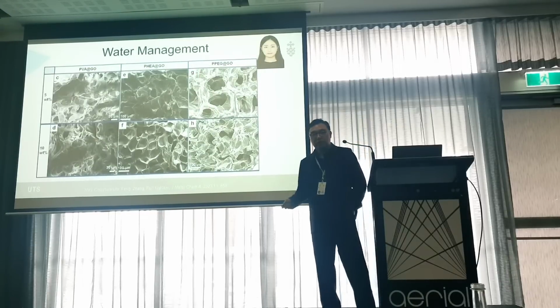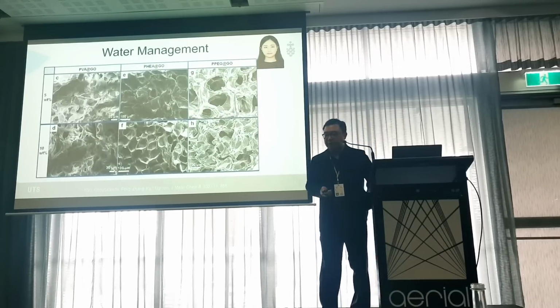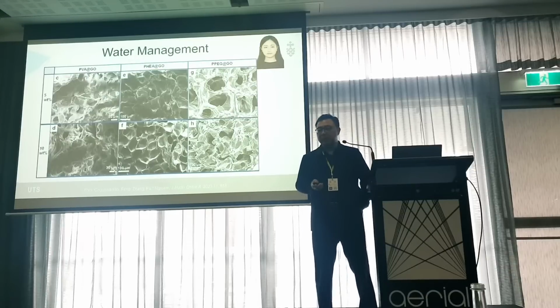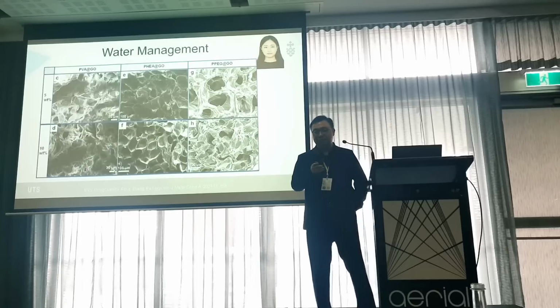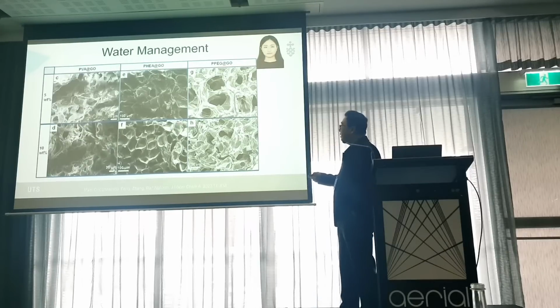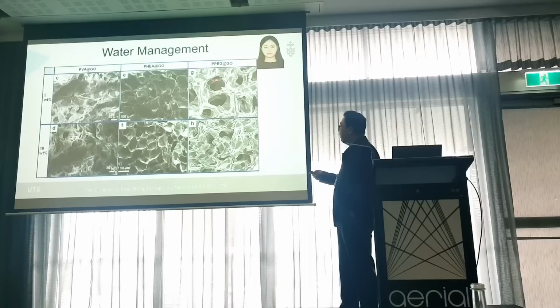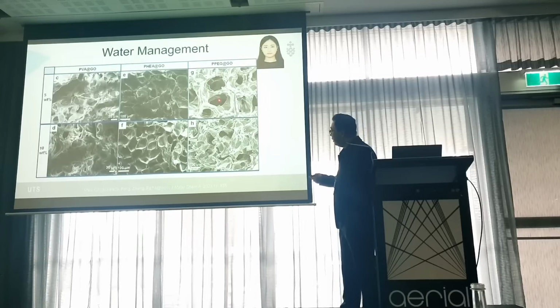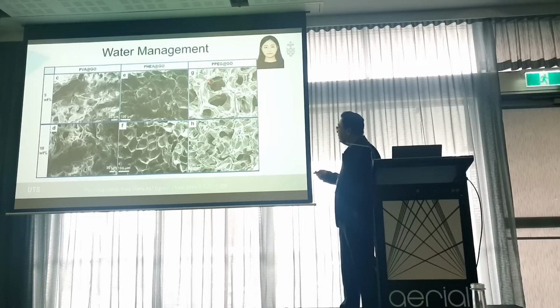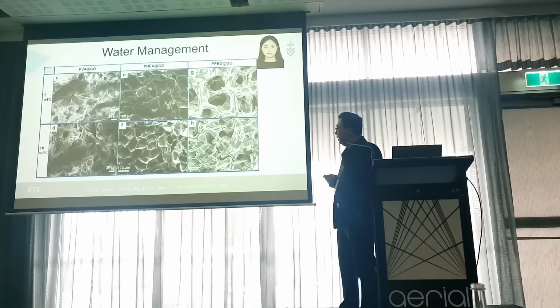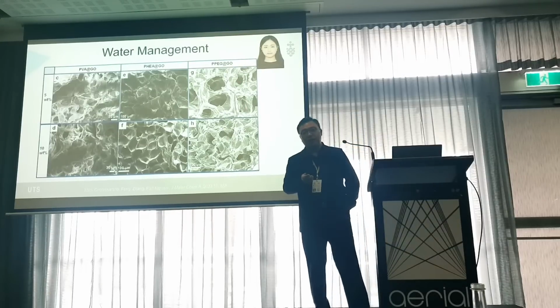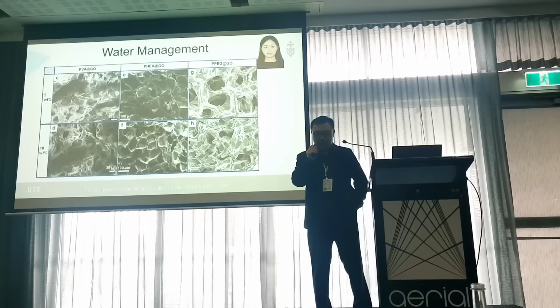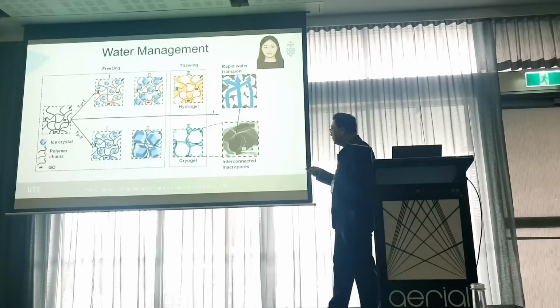So we first characterize the morphology of these hydrogel materials, as you can see from the SEM images. All the hydrogels have a micropore structure. However, interestingly, we find that the PVA and PEG composite hydrogels have relatively larger pore sizes, and all the pores are interconnected, as you can see from this image. So this structure is expected to show faster water transport. So what's the reason?